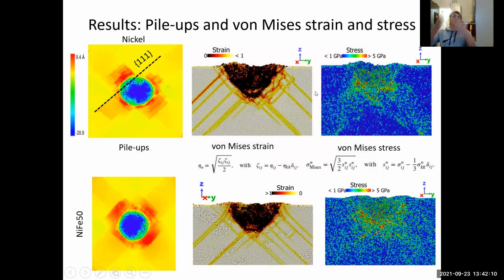So now we need to see the atomic strain, by computing the von Mises strain for each atom. When we are at the maximum indentation depth, we notice that the maximum strain, oh, sorry, this is inverse. I apologize for this, because the maximum strain is here underneath the tip. And then you have the other atomic distribution for the von Mises strain. And for the stress, you also have the same distribution underneath the tip. You have the maximum stress.